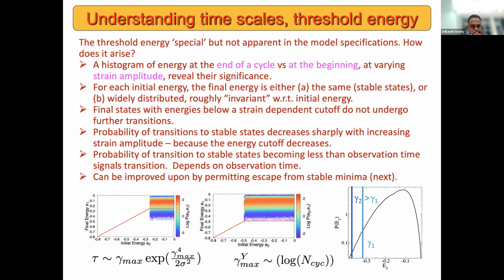Okay, and now when you go beyond a certain value of the initial energy that is fixed by the amplitude of the strain, what one finds is that one makes transitions stochastically to different energy minima, and these energy minima, or mesostates, have energies that are distributed roughly insensitively to the initial energy. So in other words, regardless of what the initial energy is, after one cycle, I find myself in a final energy which is taken from essentially the same distribution.